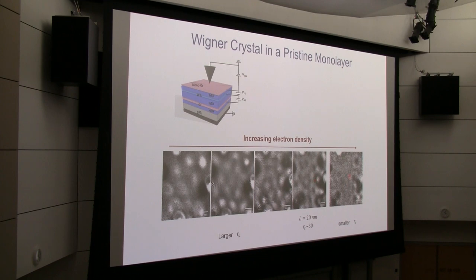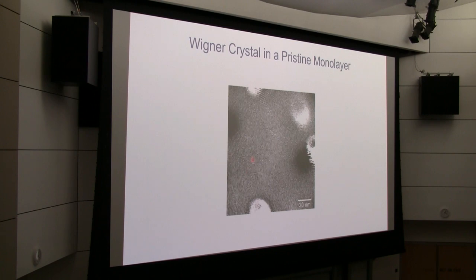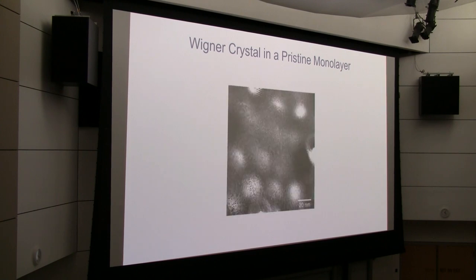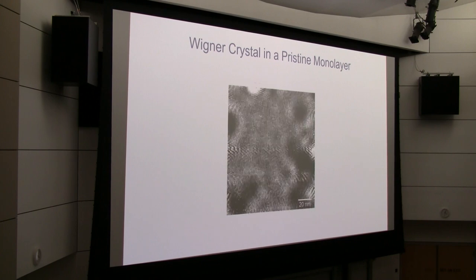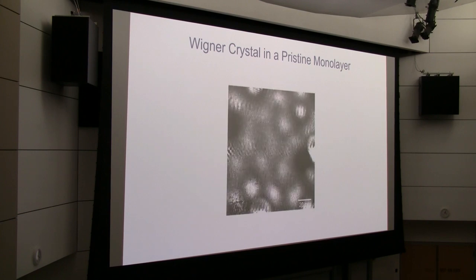And when you increase the density further, it changes from a crystal phase into a Fermi liquid phase, and you see a homogeneous distribution of charge. To show this more carefully, we can actually put it in a video, so maybe you can see the evolution more clearly. At low density, basically, you have a small lattice. And when you increase the density, you can see the evolution of the Wigner crystal, until at high enough density, it starts to melt.